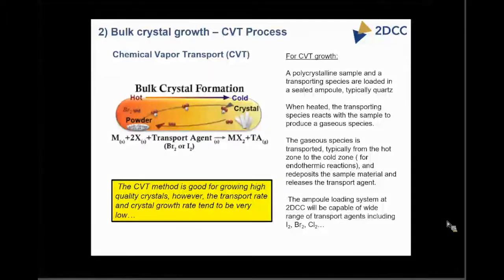When you heat this up, the transport agent reacts with the source material, forms a gaseous species. And there's a hot section and a cold section. The material is transported down this temperature gradient, depending on if it's an exothermic or endothermic reaction. Typically, most of these are endothermic. You redeposit the material on the cold end and then release the transport agent and set up a circular cycle here for transporting material. There are 2 systems for chemical vapor transport that are going to be installed.